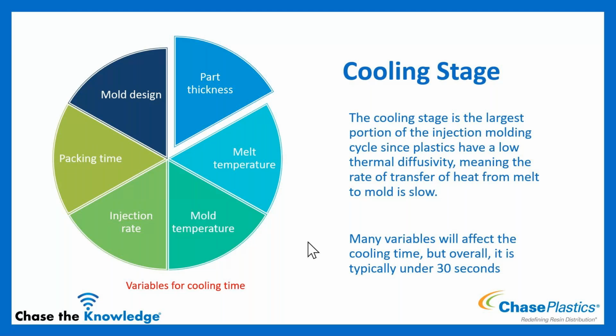So there's a lot of variables that will affect that cooling time. Thickness, melt temperature, mold temperature, injection rate, packing time, mold design. This is a PVT relationship, pressure, volume, temperature. And you will typically see this around 30 seconds or under. For thick wall parts, that might get up into the minutes, just depending on your specific geometry and scenario.